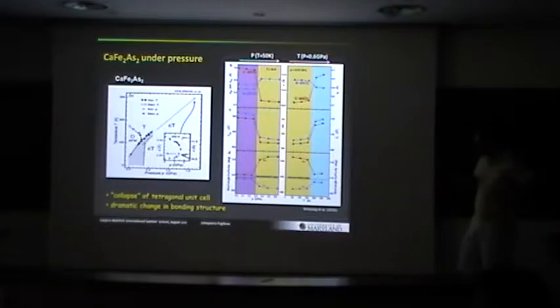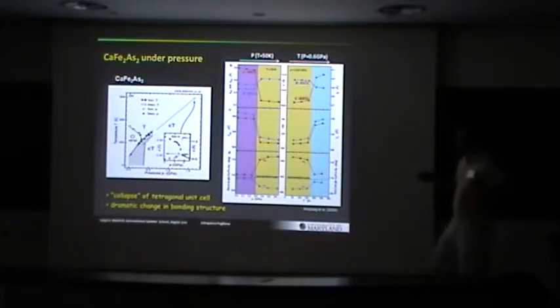Okay, here's some background. Going a little further from yesterday, this particular compound, calcium iron 2 arsenic 2, is a parent compound. It has a Néel temperature of 160, 170 Kelvin, just like the other 122s. And you can dope this in a transition metal site, just like it was shown yesterday, to induce some superconductivity. You can apply pressure in the same way, but one thing happens that's very different than the other compounds. When you apply pressure to this material, you run into this very severe structural transition. So that's shown up here.